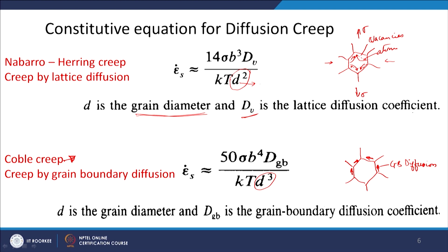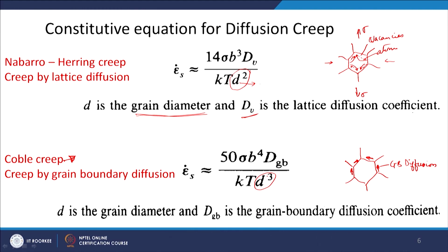In Nabarro-Herring creep the grain size had an exponent of 2, whereas in this the grain size has an exponent of 3. So Coble creep is more influenced by the grain size, whereas NH creep has less dependence on the grain size. As the exponent increases, you can understand that it will have more effect on the strain rate. If you want to compare, in the same material, where NH creep takes place and where Coble creep takes place, you should do an experiment where you are refining the grain size.